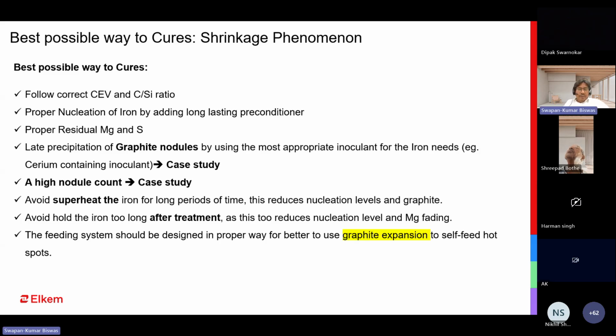Also, to overcome microporosity, you have to select an inoculant which can provide secondary graphite precipitation. In most cases, calcium barium gives a huge number of graphite precipitations at the initial stage, and later the formation of nodules or flakes is very low. So you have to select an inoculant that can provide graphite precipitation from the start to the last stage of solidification. That will help to control the microporosity.